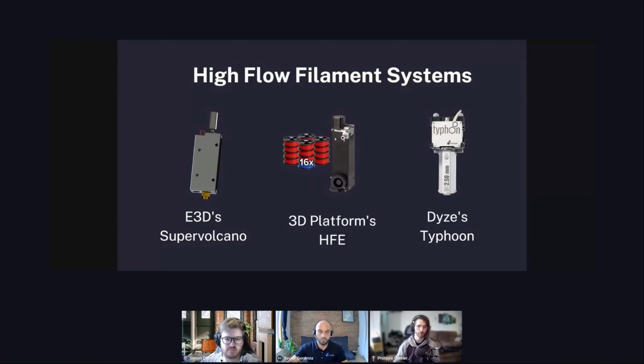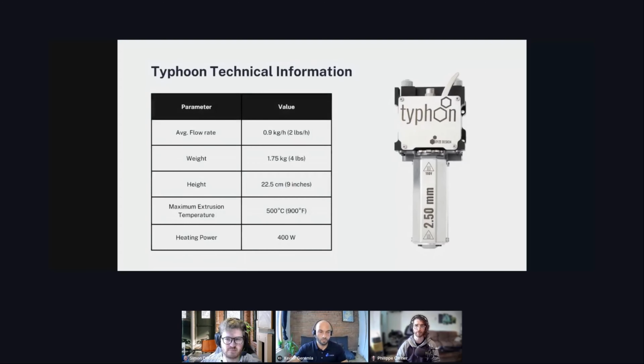There are already a few solutions on the market, each with their own advantages and disadvantages: E3D Supervolcano, 3D Platform's HFE, and our own Typhoon extruder. Typhoon is described as a high flow and fast print all-in-one extrusion tool head specifically designed for industrial large-scale 3D printers. This print head is designed to extrude 2.85 millimeter filament, is compatible with standard firmwares, and is capable of delivering an average flow of 200 cubic millimeters per second, which is about 0.9 kilogram per hour. This means quicker print at high deposit rate.